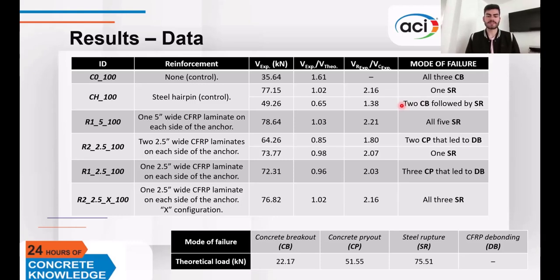The systems that evidenced the latter failure mode did not manage to achieve a strength similar to that of anchor rupture. This shows uncertainty in the response of cast-in anchor reinforcement, as the cause of this variability is attributed mainly to minor differences in the installation, even if great attention was paid to this process, ensuring contact between the anchor and the hairpin and guaranteeing minimum concrete cover. Additionally, specimens with total width of reinforcement concentrated in one strip on each side evidenced steel rupture every time, developing an increasing strength of 2.21 times that of unreinforced specimens.